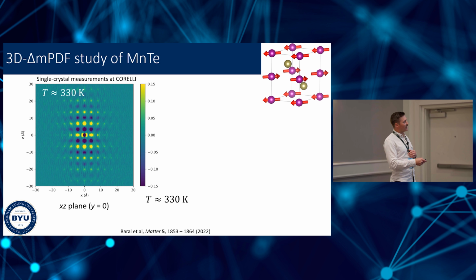So the bright spots mean parallel alignment, the dark spots mean anti-parallel alignment. And you can see this is the XZ plane, so it's kind of like looking at this face right here. As we move along the C axis in the Z direction, we alternate between up and down spins. So we see these alternating colors, but within the plane, the spins are aligned with each other. So we have the same color within the plane.